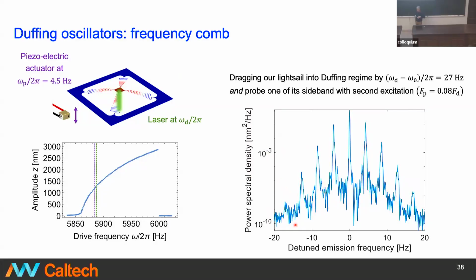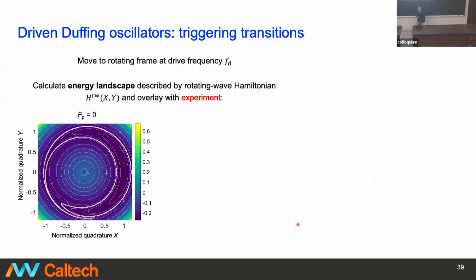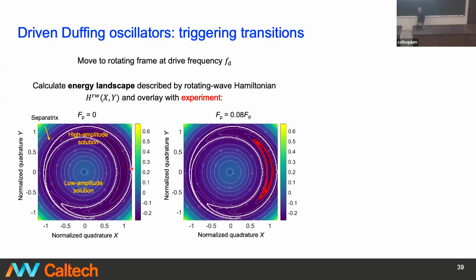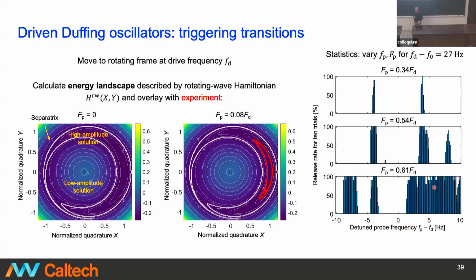So this is a very interesting oscillator. It's a structure that has quite high compliance, quite large displacement, but quite high Q. It has some interesting properties, and that leads to some very interesting phenomena that we saw. If you cast the motion into a rotating frame and look at the dynamics as a function of the two quadrature elements, what you see is that there are two stable solutions, this high amplitude and low amplitude solution, and a so-called separatrix, a stability boundary between those two solutions. As you drive harder, you expand the high amplitude phase space for these two motional quadratures. We're able to map out the resonance and the sideband frequencies and ultimately the excitation of these frequency combs for these structures.